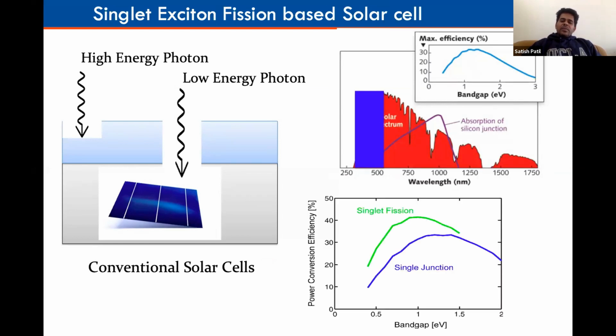So there are calculations people have done. This is what I have shown here, power conversion efficiency versus the band gap. In the plot, you see that it's band gap dependent. At the blue part of the spectrum, you see that around 1.4 eV you get an efficiency close to 33%. But if you make a very low band gap material, you get a very low efficiency, and with a wide band gap, you also get a low efficiency. If you use the concept which I'm proposing here, singlet fission based solar cells, you can really jack up the efficiency to more than 40%. So this is something very exciting for us.